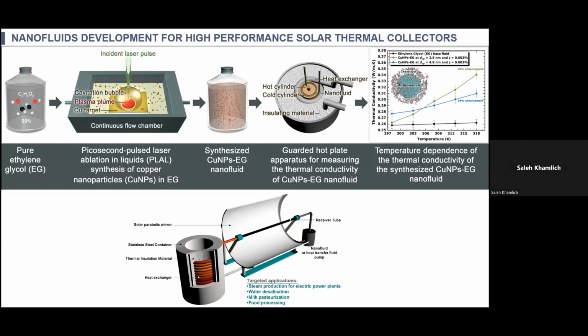And we use, as I mentioned, different wavelengths. And this is what we found. This is the temperature, this is the thermal conductivity. For a sample made with 1064, it has nanoparticles with a diameter of 4.8. It gives us an enhancement of 18% at a temperature of 380 Kelvin.